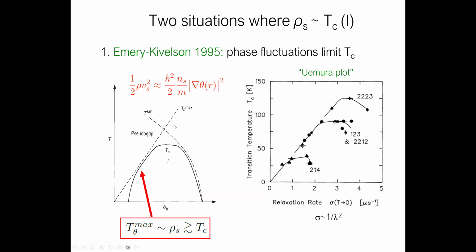So in this underdoped regime, you would get a nice proportionality, and that's seen in the famous Uemura plot, where you plot the transition temperature now versus something that's proportional to the superfluid density rather than the other way around. And you also see this backfolding effect, the so-called boomerang effect, on the overdoped side.